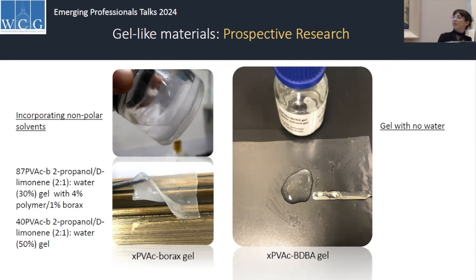But you will get this syneresis, which is this expulsion of liquid from gel. You can see though that hasn't had an effect on the gel's working properties. Like you can still produce quite a good flexible moldable gel from that. You just might want to blot it dry, a little bit wet and decant the solvent from the jar.